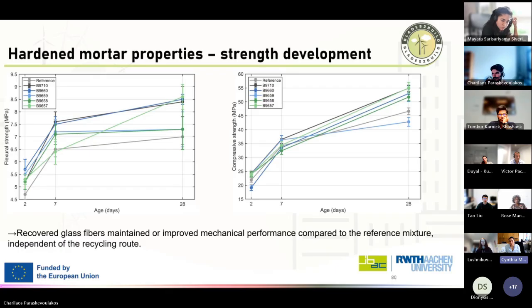Please just try to focus on the left-hand side with the flexural strength. Look for the gray line, and you will see that this gray line, without the fibers or the wind turbine blade waste, has actually the lowest performance. Everything with the added fibers has the higher performance. Okay, so more or less, you will see a very similar trend concerning the compressive strength.